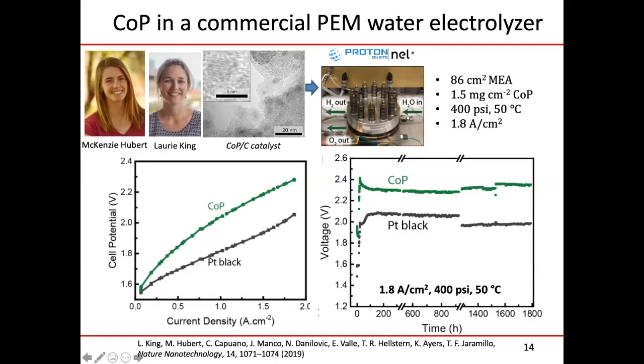And then the question was, what about long-term durability? And so they just ran this thing for about 1,800 hours before it was time to shut down the experiment because the project ended. And we saw absolutely no signs of degradation. It was just absolutely a very smooth operation all the way through, no catastrophic failure at the end. I am curious how long it would have lasted, but that wasn't in scope for that particular project.